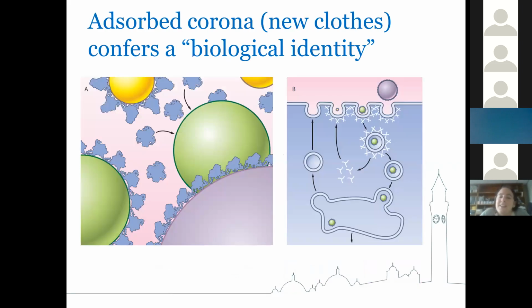Added to that then, as I said, is this idea of the adsorbed corona of biomolecules. So when we take our pristine nanomaterial that we made in the lab and we put it into either a formulation or into cell culture medium to do an exposure, that pristine surface very quickly gets decorated with biomolecules from its surroundings. And if that's in a human tox scenario, it'll likely be some of the serum proteins, it may well be some membrane proteins and so on that bind, as well as other biomolecules, so lipids and small molecules will also be in there. But what happens is that our synthetic identity that we've now characterized gets altered and evolved by a biological identity. And it's these proteins and other biomolecules that are bound that determine which pathway the nanoparticles use to enter cells.